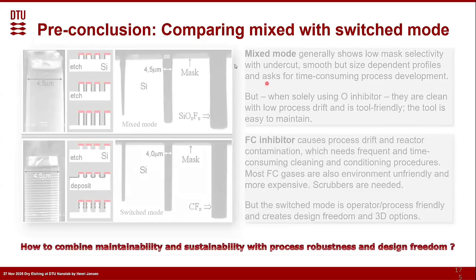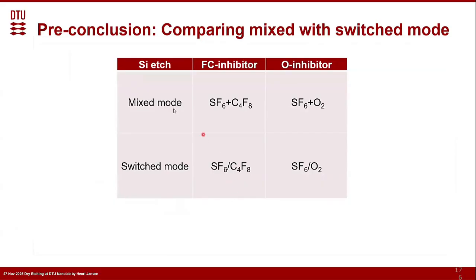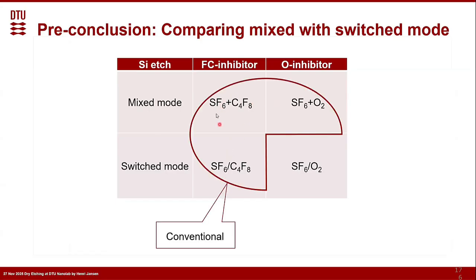So this one is, let's say, good for the machine, and this is good for us. How can we combine this? Let's go back to how we etch silicon in the mixed mode or in the switch modes, and we have the fluorocarbon inhibitor with C4F8, and we have the oxygen inhibitor. We know these. This is conventional. That was the original one, done 40 years ago, and then these came in later, also cryogenic. And then this is the Bosch process.